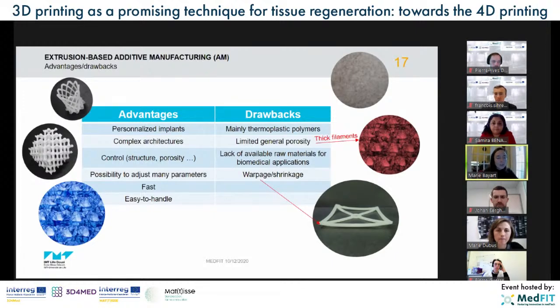We can use mainly thermoplastic polymers, so it reduces the possibilities. It has a limited general porosity because we deposit thick filaments of droplets, as compared to techniques such as electrospinning that can reach like 90% of porosity. Here we can reach a little bit less. And there is a lack of available raw materials for biomedical applications, so we need to develop new ones. And also there are phenomena of thermal distortion like warpage and shrinkage, as you can see on the picture. But here in our case, it's very limited because we are using amorphous polymers.